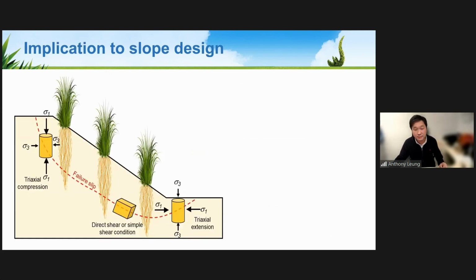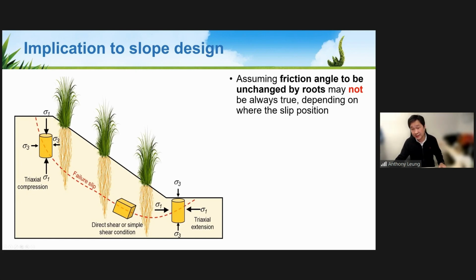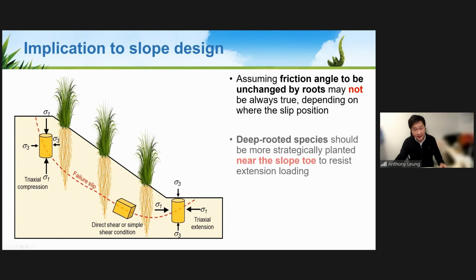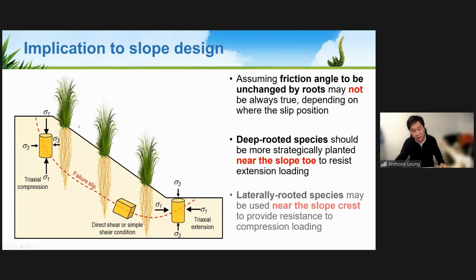So coming back to our engineering problem, one piece of advice we could take is that assuming friction angle to be unchanged by root may not always be true, depending on where the slip position we are talking about. For direct shear position, yes, maybe you can assume nothing changed in the friction angle. But for the crest and the toe, the friction angle could have been changed by the root. And if you select a deep-rooted species, we would advise you to put it near the slope toe, because at that position, extension is the more preferred failure mode. So the reinforcement will be more significant. By the same token, if you have a laterally rooted species, you could put it near the slope crest, because at that position, you will have a perpendicular direction between the major principal stress and the root orientation. That will give you the highest root reinforcement effect.